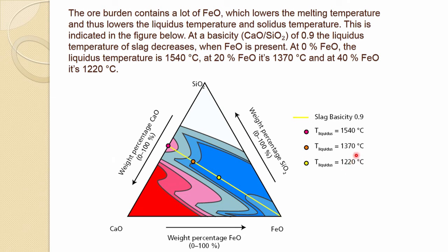So, this shows the importance of ternary and quaternary diagrams, because using them one can really select the proper composition of the slag to operate the blast furnace in a much smoother way, and can take corrective action at various stages. As you have seen, the primary slag composition is quite different, the bosh slag composition is again very different, and when we reach the hearth slag, that composition is also quite different.